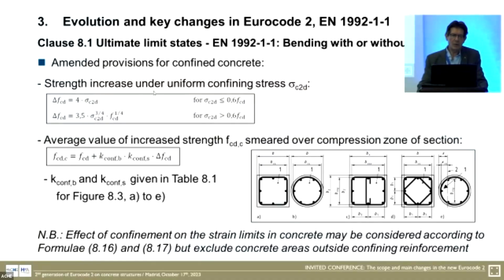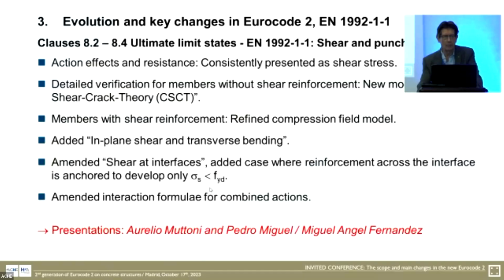We have amended these provisions. We give the simple provisions up here if you have a member which has a uniform confining stress on the entire cross-section. But in practice, of course, this does not happen with the cross-sections and the layout of the transverse reinforcement. So for these practical cases, we give these coefficients K, which allow you to calculate an average, a smeared value of the increased strength, which is valid for the entire compression zone. These values of the coefficients K are given again in a table.